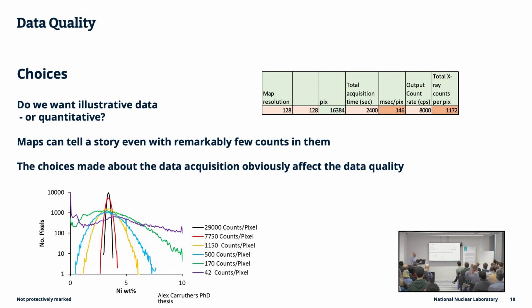This is an example from Alex's thesis, where the figure at the bottom here, and this is what I was alluding to about, do we want illustrative data or quantitative data out of our maps? And the spreadsheet at the top there just runs through a really basic calculation on how many X-rays you're going to get into a pixel in a given amount of time. And the figure at the bottom illustrates that really nicely in terms of the uncertainty in the quantitative composition.